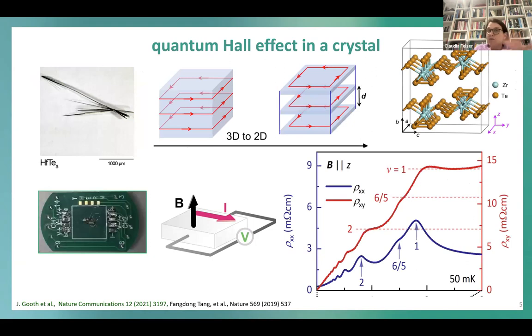So surprisingly for me, you can see even this effect in crystals. I always say, Christina, you are a solid-state chemist, and there might be some other solid-state chemists. So we make crystals. And if you measure the crystals at lower temperature, this effect appears here, for example, in hafnium telluride, a very common simple chalcogenide crystal. So you see exactly the same effect, even by doing a very simple PPMS measurement on a single crystal.